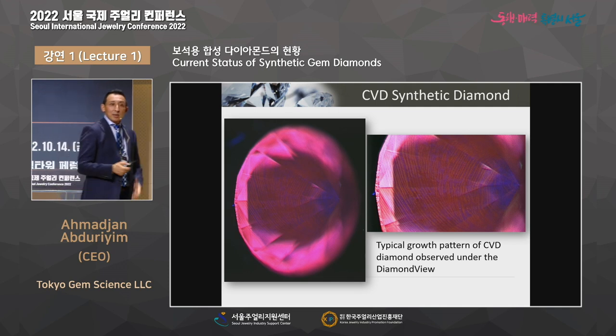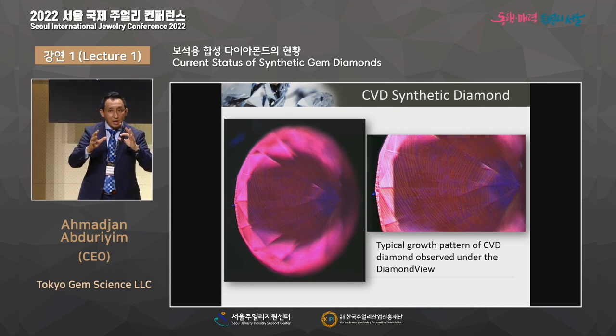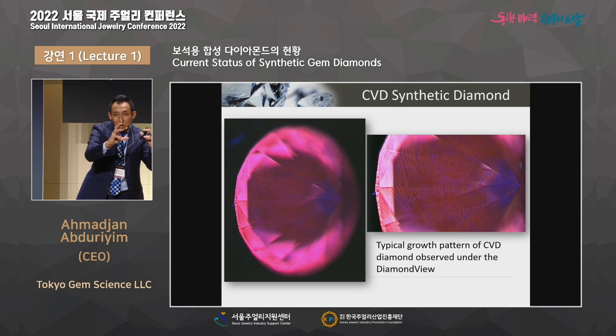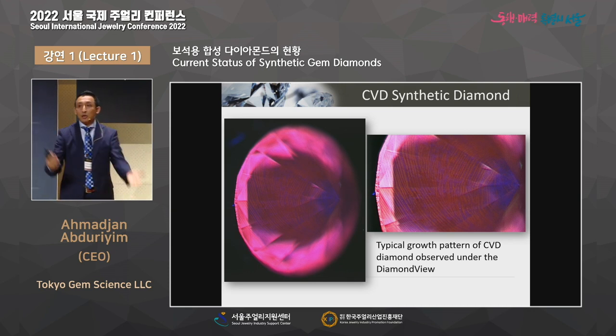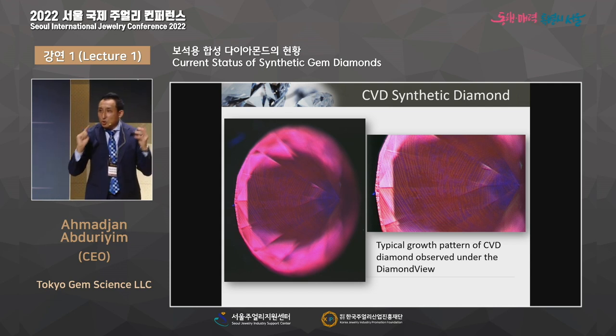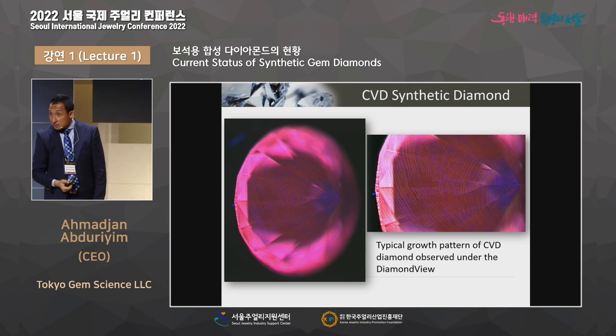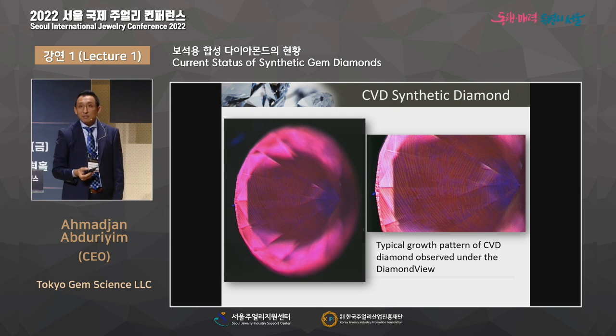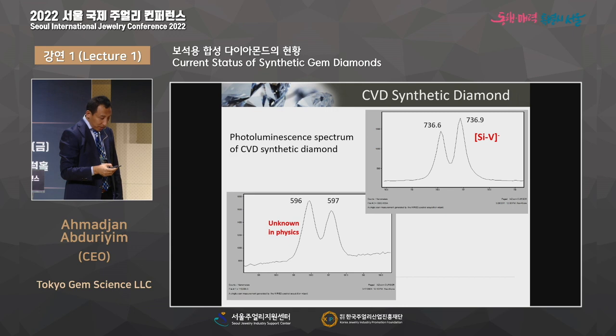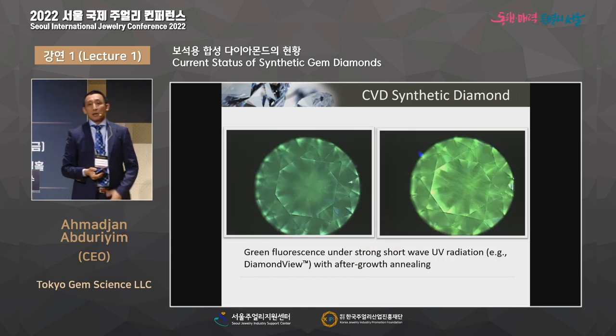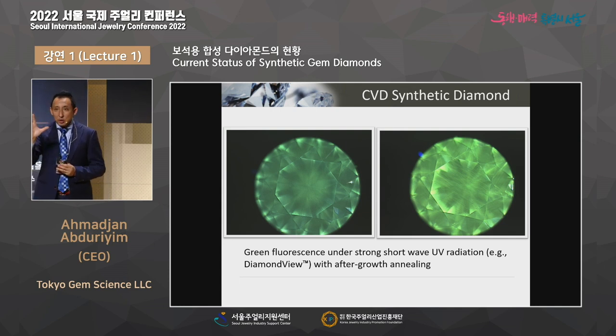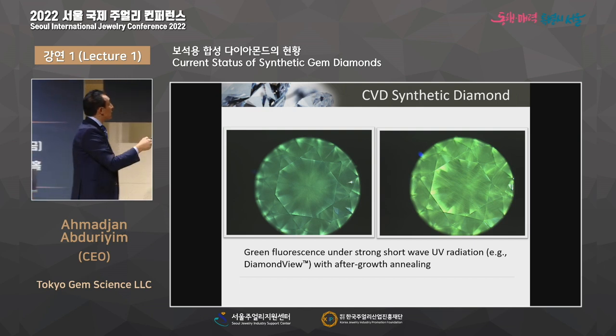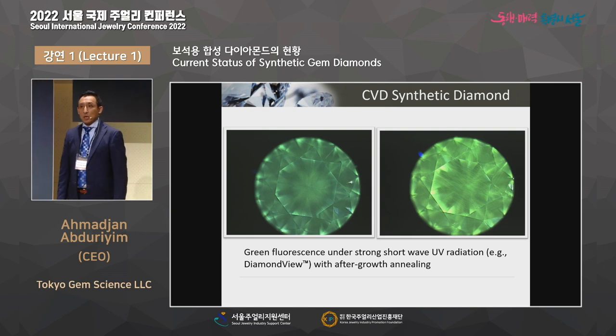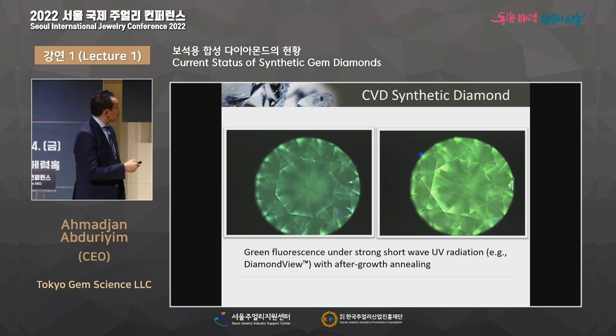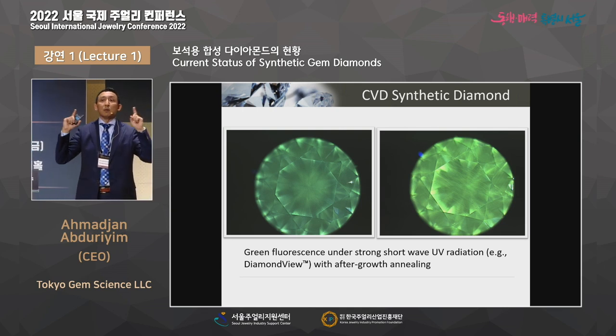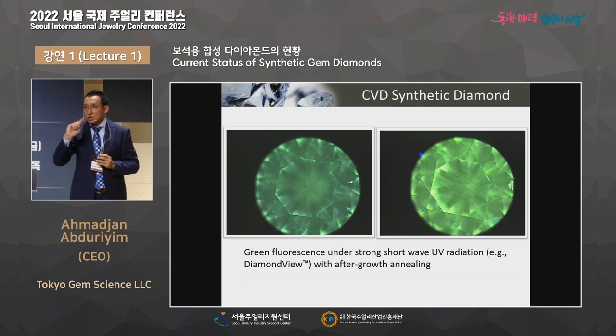Very important. However, as I said, CVD diamonds mostly show a brown color right after growth. They try to remove the brown to make them colorless. Actually, this red fluorescence really helps us pick up CVD diamond. It's very interesting because natural diamond never shows this strong red fluorescence, which helps the lab gemologist pick it out. However, after the treatment, this slide, the red color is gone. Destroyed by the HPHT process. So you only see this kind of bluish green or greenish fluorescent color under the DiamondView instrument. You can never see such a red color anymore. After the treatment, your CVD diamond never shows a red color. Please remember that.